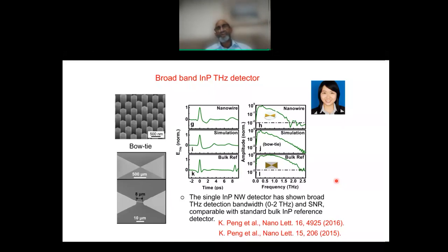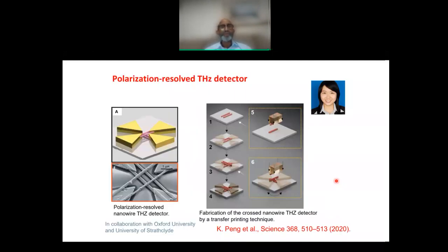Most recently, during her postdoc at Oxford, Kunpeng has demonstrated polarization-resolved terahertz detectors. In this case, she makes her initial detector like this one here. The challenge has been to have another nanowire at 90 degrees to this one. But when you do this, the top nanowire should not be physically in contact with the bottom nanowire, for example. So that's what she spent a lot of time working on with my colleagues at the University of Strathclyde and Oxford, and then we were able to fabricate these structures. Again, she comes with this stamp, and my colleagues in Strathclyde are able to locate them after fabrication of the first device.